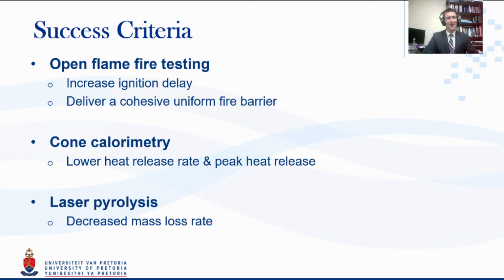On the laser pyrolysis side, we wanted to look specifically for decreased mass loss rate, because on that small scale, where it's exposed to direct laser pyrolysis, this simulates the charring and the thermal behavior and the thermal shielding very well, which we actually succeeded quite well with in our materials.